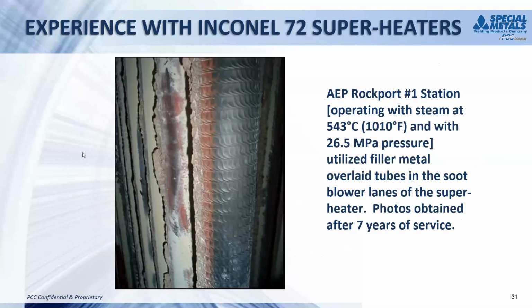Next slide. This is another example of some experience that Special Metals had with some Inconel 72 on the superheaters. As you can see in that picture, obviously the tube that's shown up front was blasted and cleaned up a little bit, but you had some pretty heavy deposits of this melted salts, if you will, depositing on these superheaters. But after 7 years of service, very little or no attack on the Inconel 72 tubes.